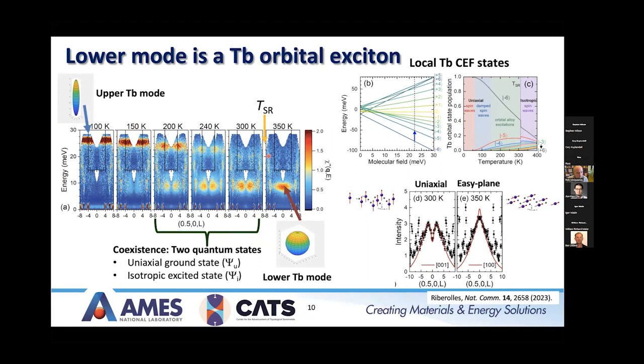Again, this is just another slice looking along a different direction. You come down, you see the coexistence of the two modes, and this coexistence of the two modes actually corresponds to the coexistence of two states, this uniaxial ground state that we have and an excited state that's more isotropic. And then once you get past the spin reorientation transition, all that you're left with is this isotropic lower terbium mode here. And you get the ferromagnetic state following the manganese easy plane anisotropy, where the manganese and the terbium both lie in the plane.